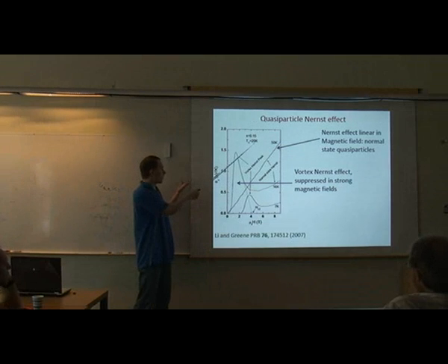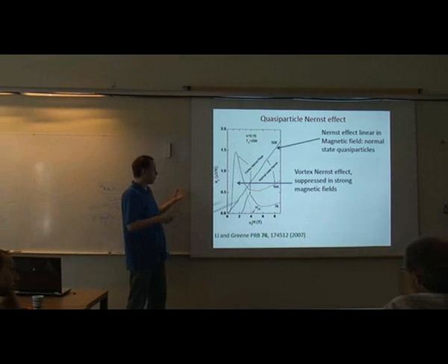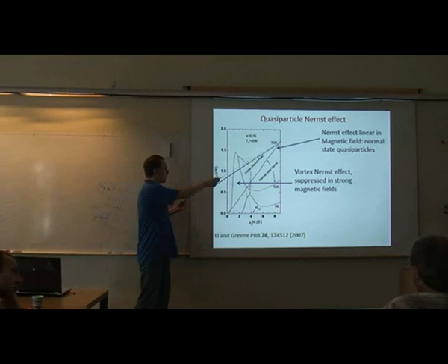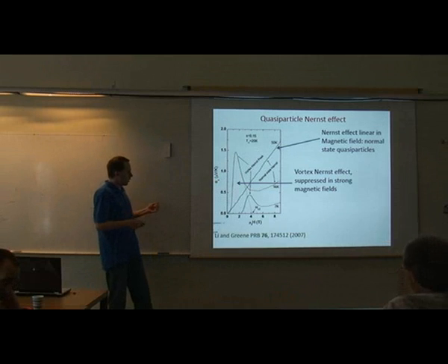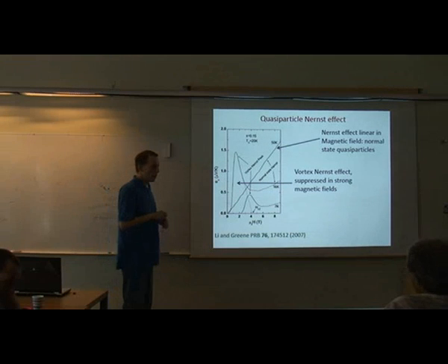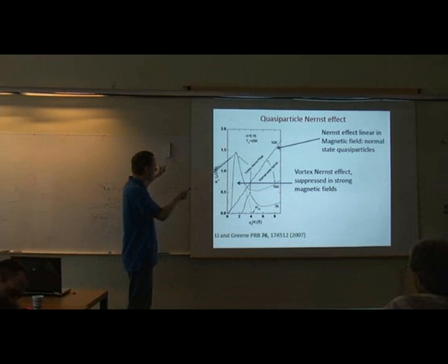Once you have 25 Kelvin, it will decay. Once you have 30 Kelvin, it won't almost be visible. At 50 Kelvin, as you see here, you have only the quasi-particle signals. But on the electron-doped side, the fluctuation should be weak anyway, right? It's weak anyway, that's another point. It's not extremely weak. You see still quite a strong Nernst signal compared to the quasi-particle effect.